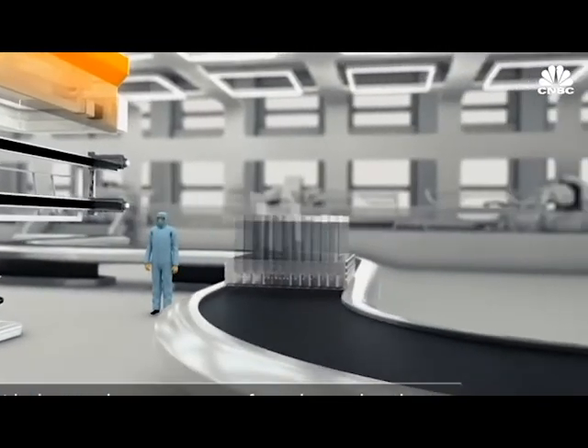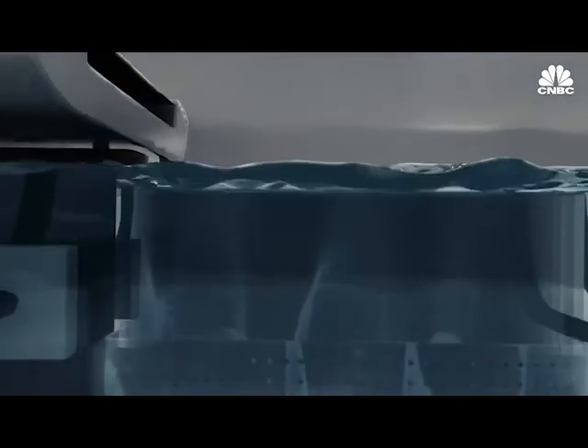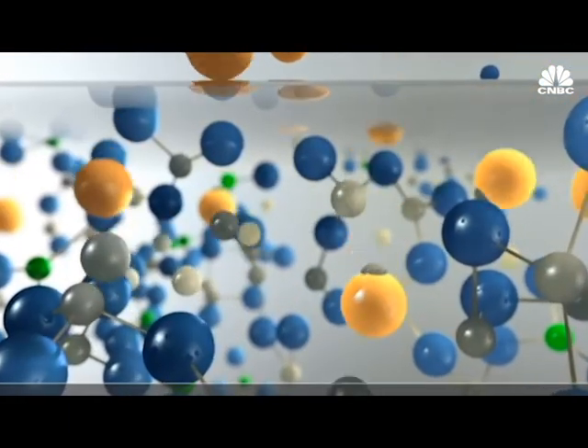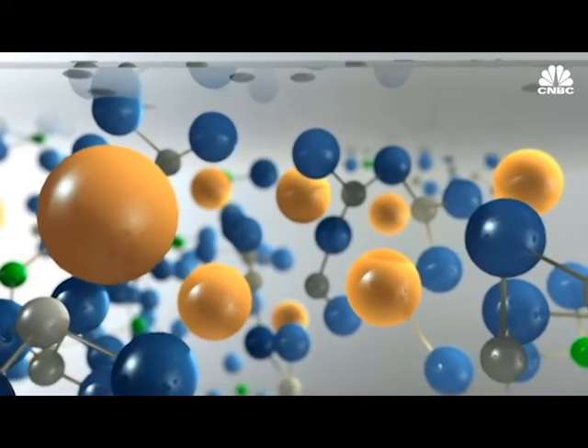Next step, after fusion draw finishes, the Corning Gorilla Glass undergoes ion exchange to increase its strength. Aluminosilicate compositions like Gorilla Glass contain silicon dioxide, aluminum, magnesium, and sodium. When the glass is dipped in a hot bath of molten potassium salt, it heats up and expands. Both sodium and potassium are in the same column on the periodic table of elements, which means they behave similarly. The heat from the bath increases the migration of the sodium ions out of the glass, and the similar potassium ions easily float in and take their place.